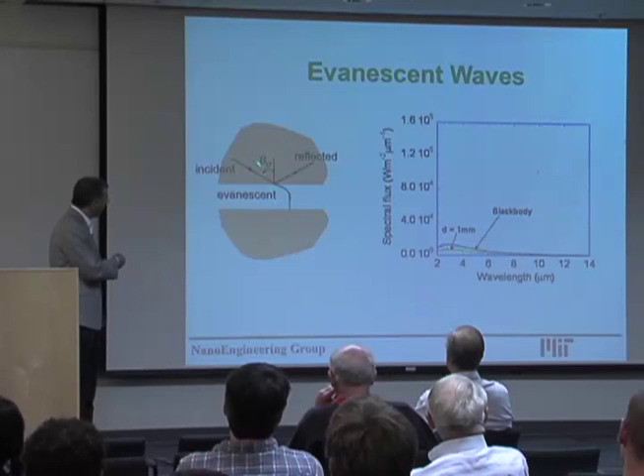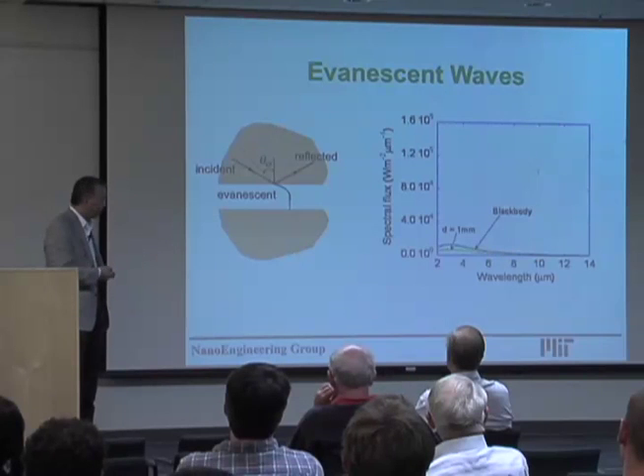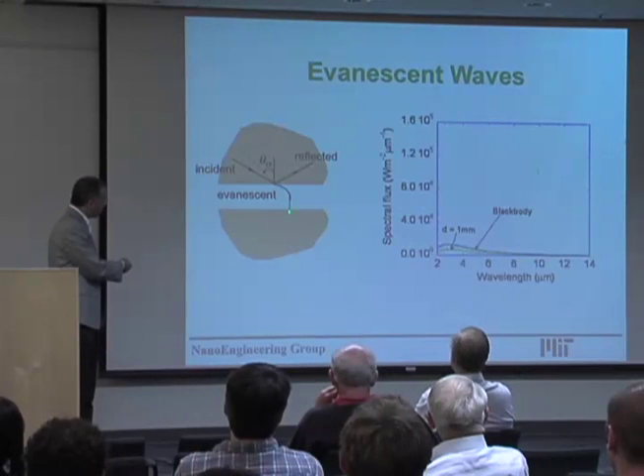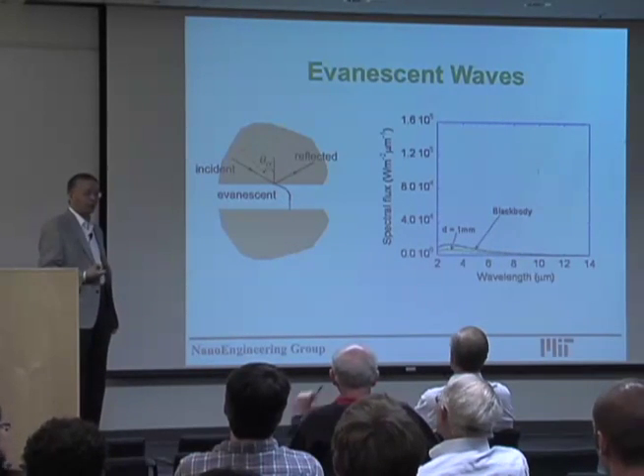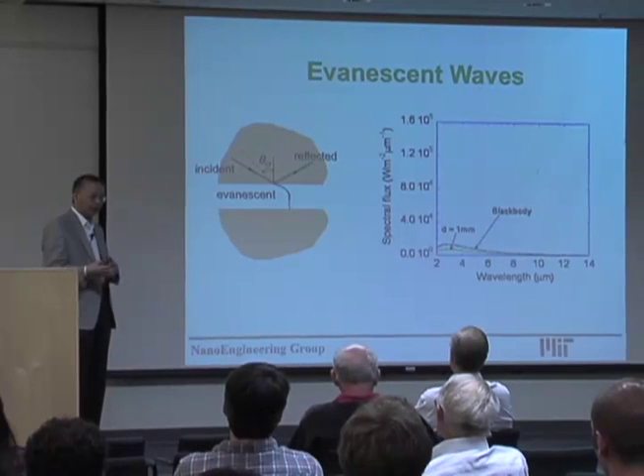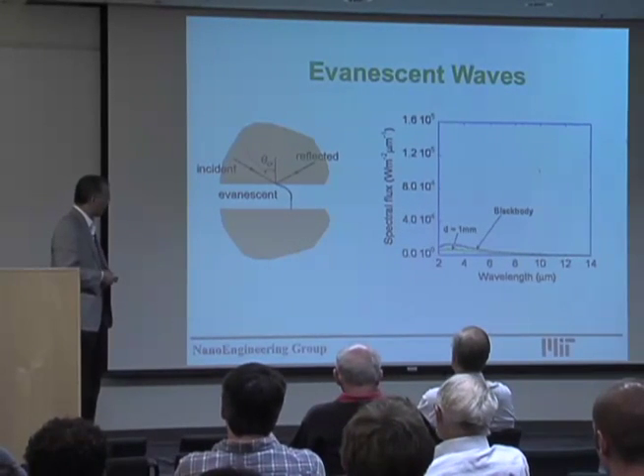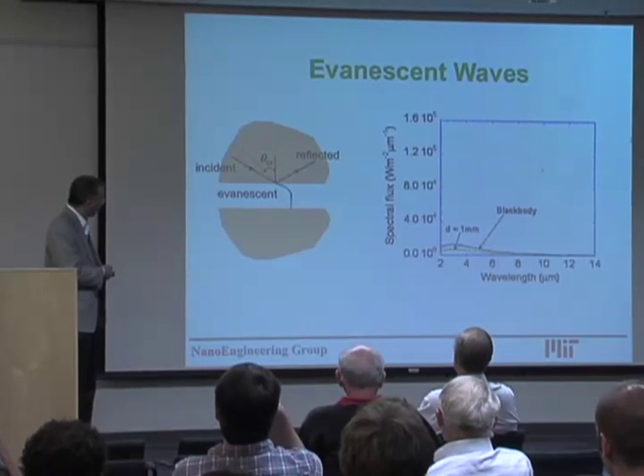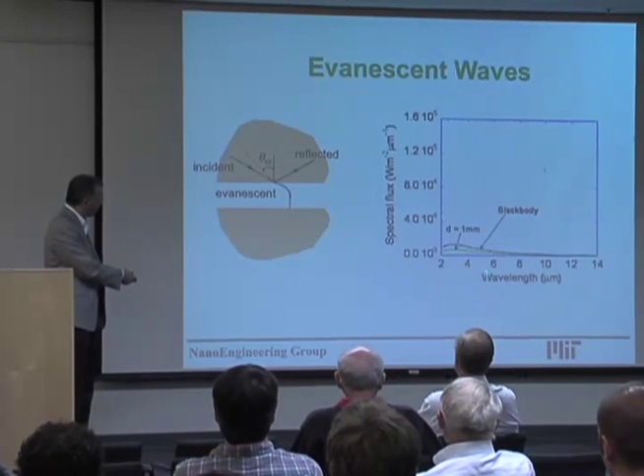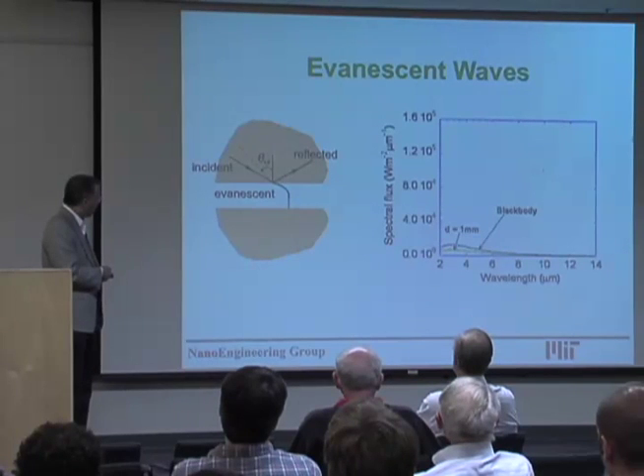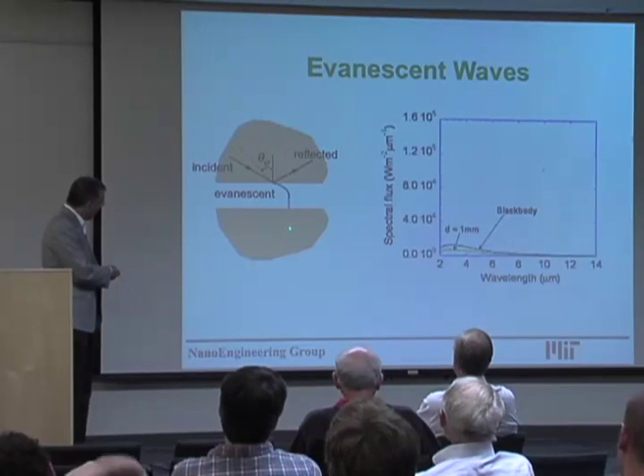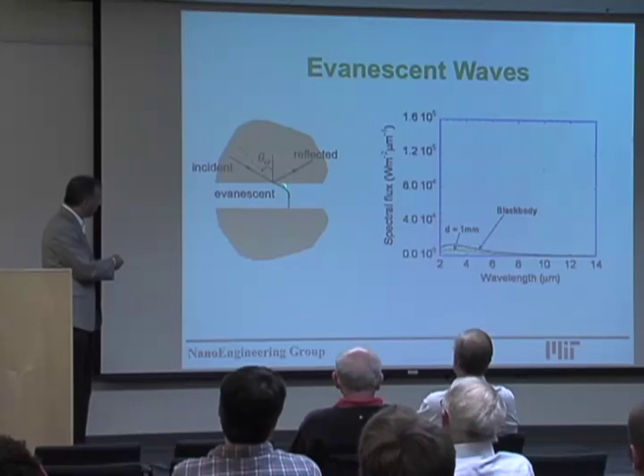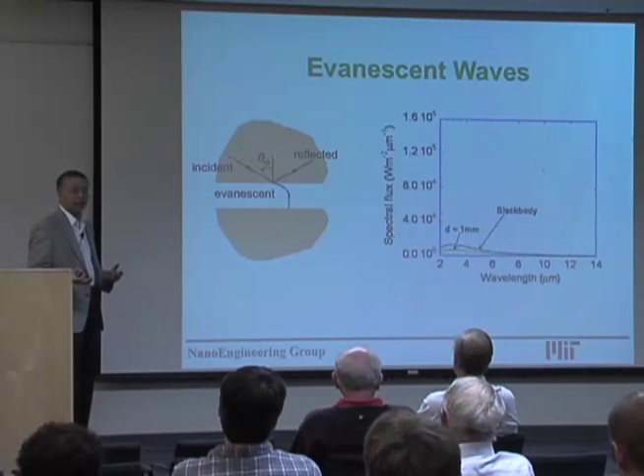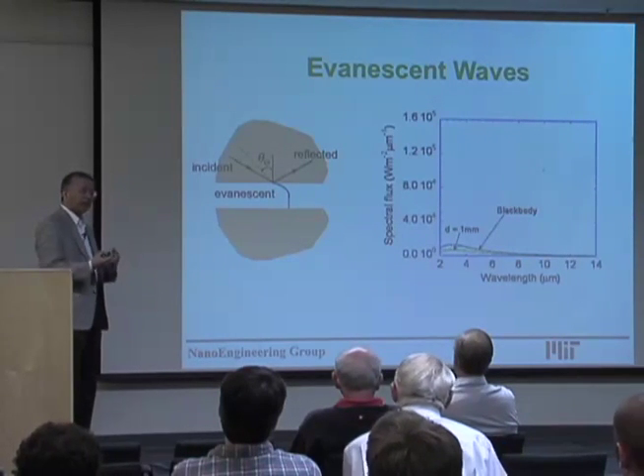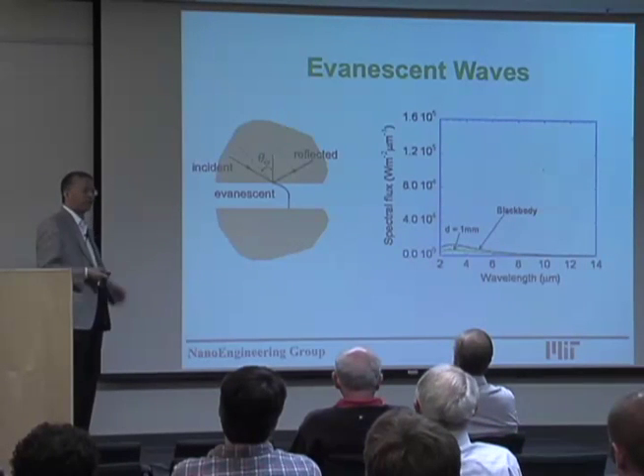And when the incidence angle is larger than the critical angle of incidence, there's an evanescent wave. It's just an evanescent wave that decays rapidly over the order of wavelengths. So normally, they do not propagate out, and they don't carry energy. So again, when the space is far, the limit is a blackbody. However, when we bring the other surface close by before the field decays to a negligible level, then radiation can tunnel from one side to the other.